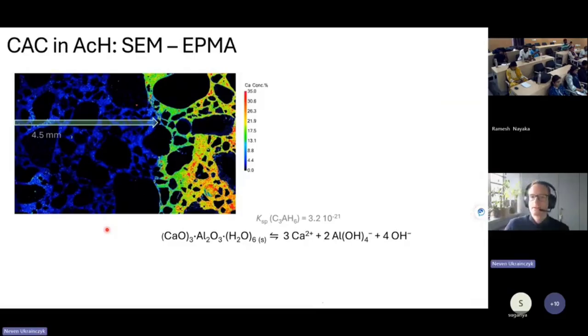So for the acid attack, here you can use microscopy also for the chemical analysis, and you can see if the acid comes from this side, you can see the depletion of calcium, decalcification, because of the dissolution of minerals. Those are the aggregates, sand aggregates. This was the mortar exposed to acetic acid, and after I think a few weeks, you can see that a 4.5 millimeter zone is completely decalcified.